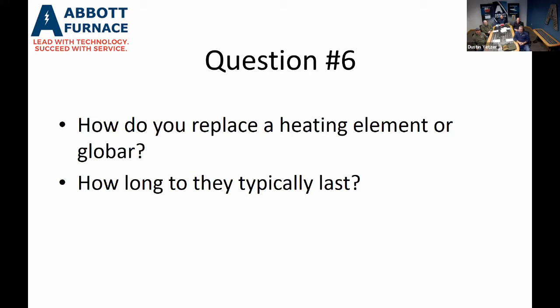Again, how long do they typically last? The biggest issue with glow bars is a lot of people take their high heats up and down in temperature. That temperature variation really wreaks havoc on glow bars. What makes a glow bar wear out faster is the higher percent output that you run on them. If you run them at full blast all the time, your glow bars usually don't last very long. That's why your first zone of the high heat is the one that eats the glow bars the most. You tend to change the glow bars out in the first zone, because that zone works the hardest to get energy into the part to heat it up to center.